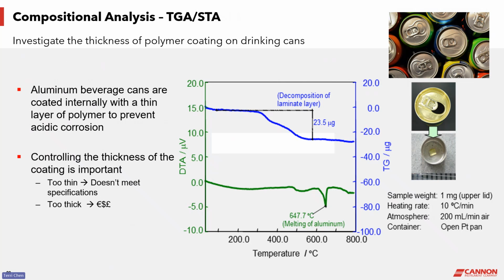Here is another interesting study of using TGA-STA analysis to quantify the thickness of polymer coating on drinking cans. Soda and Coke cans are made of aluminum. However, we all know that Coke or Pepsi are very acidic. The pH of Coca-Cola is reported to be only 2.6 to 2.7. So over time, they could cause corrosion to the surface of the can. In order to prevent acidic corrosion, people coat the surface of the can with a thin layer of polymer.